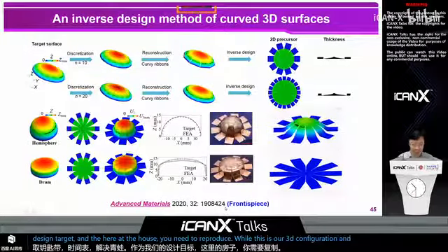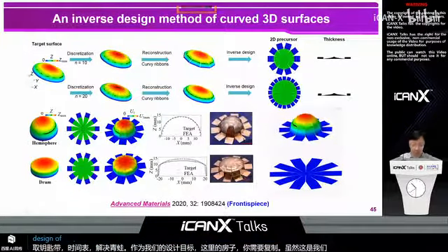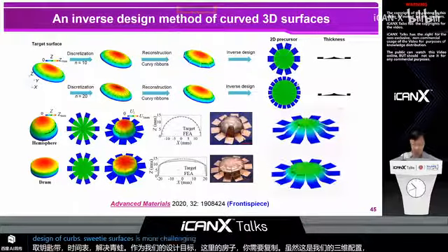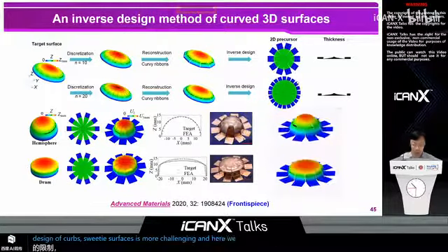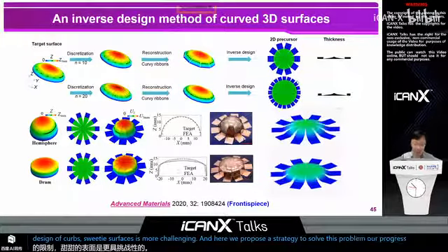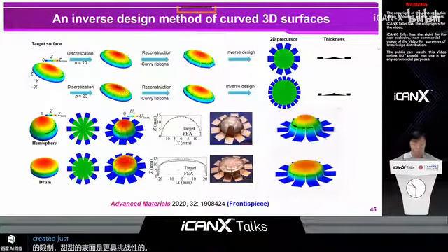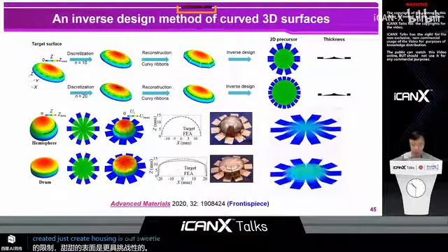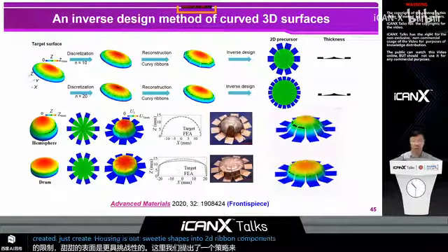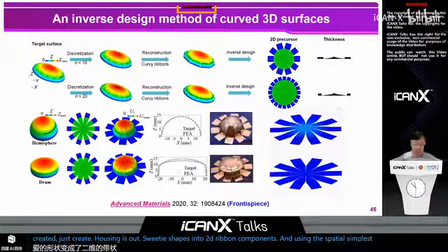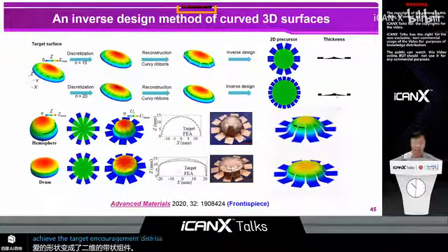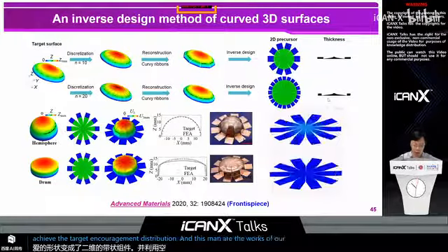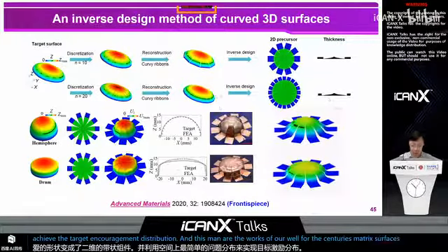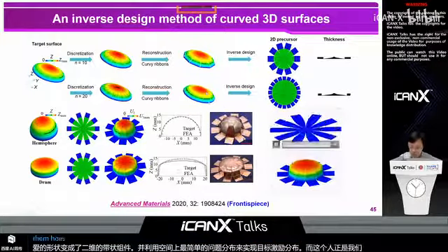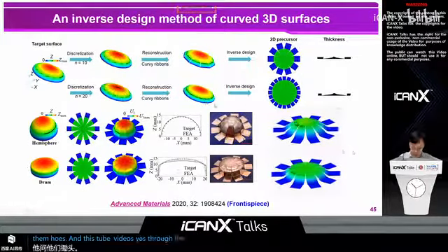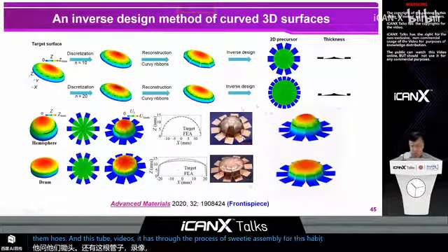And in this slide, the inverse design of curved 3D surfaces is more challenging. And here we propose a strategy to solve this problem approximately by discretizing desired 3D shapes into 2D ribbon components and using the spatial cyclic distribution to achieve the target curvature distribution. And this method works very well for the centrally symmetric surfaces. And here are three examples. And these two videos illustrate the process of 3D assembly for this hemisphere and this dome-like structure.